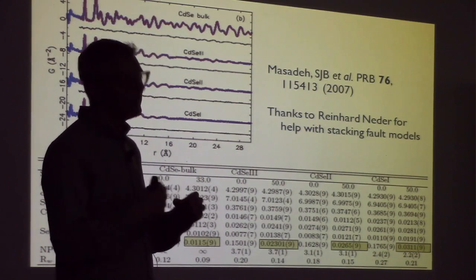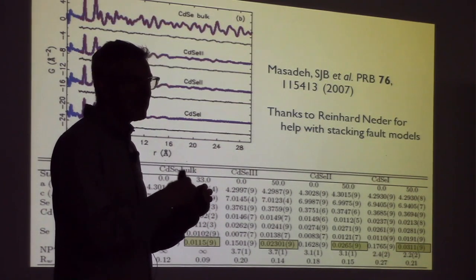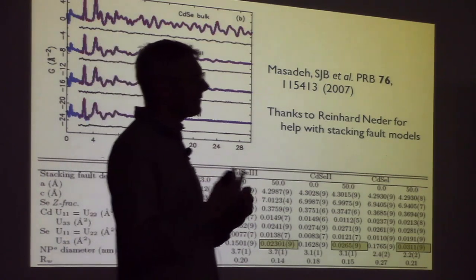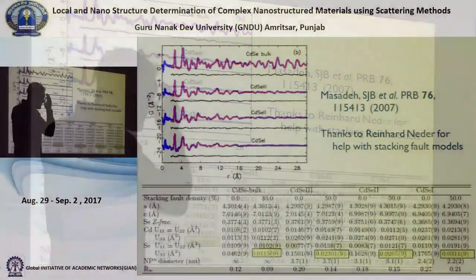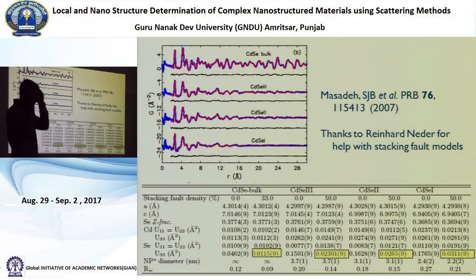And if you look at the size of the nanoparticle, what you see is that on average, you only have like 4 or 5 layers. And typically, you'll only have one stacking fault. It doesn't make any sense to actually differentiate between wurtzite and zinc blende. But people still like to use their old crystallography. They can't get out of their old crystallography mindset.